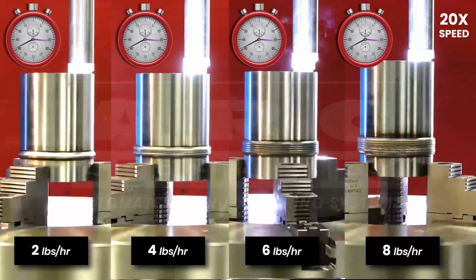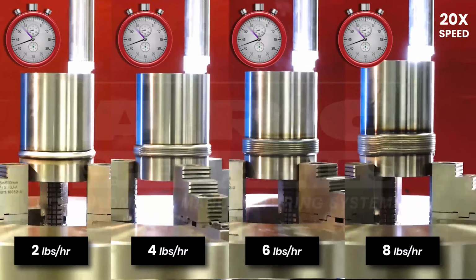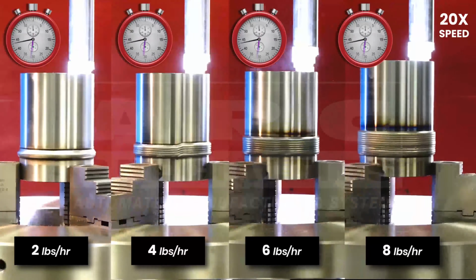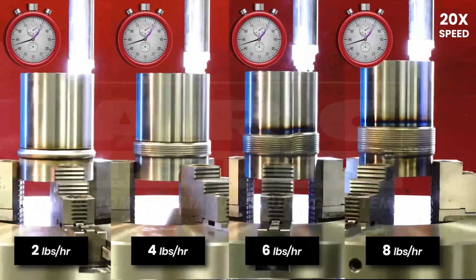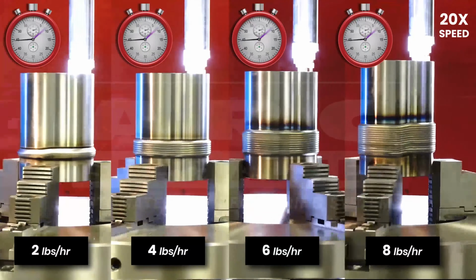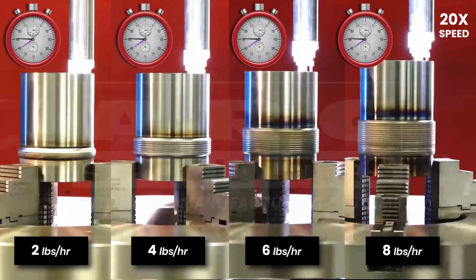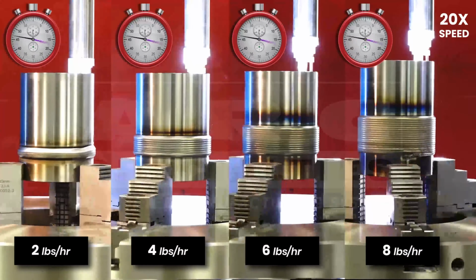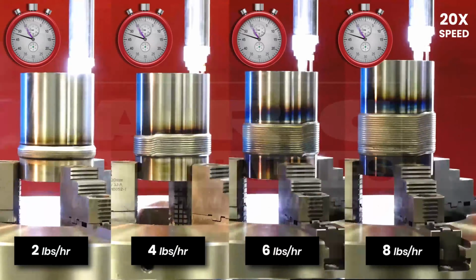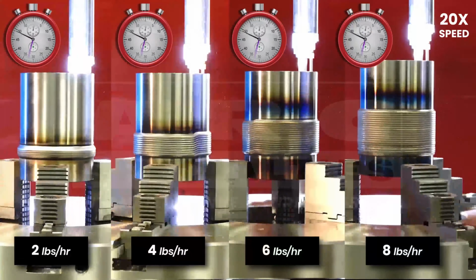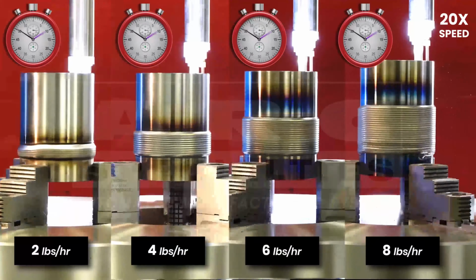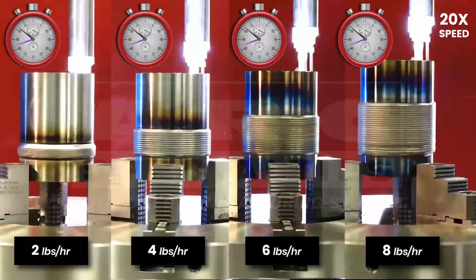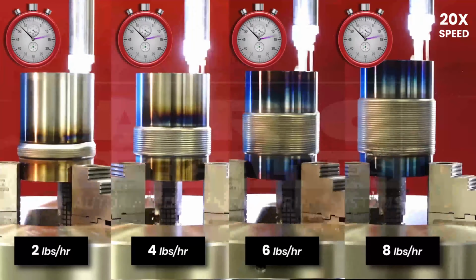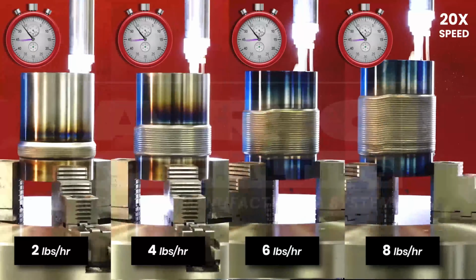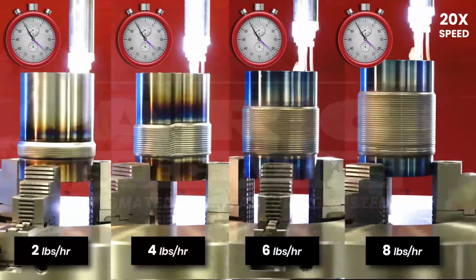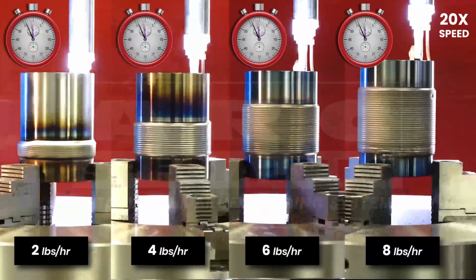Okay, so what we're trying to show here is for the same machine, all we've done is sped up the RPM, sped up the wire feed speed, and sped up the pulse rate. You made some changes in current and voltage also? Yes, obviously we have to run a higher current, and we'll run a little bit higher voltage as well. But it's not proportional. You're not going 4 times the amperage. No. In fact, we only went from 260 amps peak to 320 amps peak, and that's all it took to quadruple the deposition rate in the travel speed. And we did bring the background current up a little bit. So running a little higher background current.